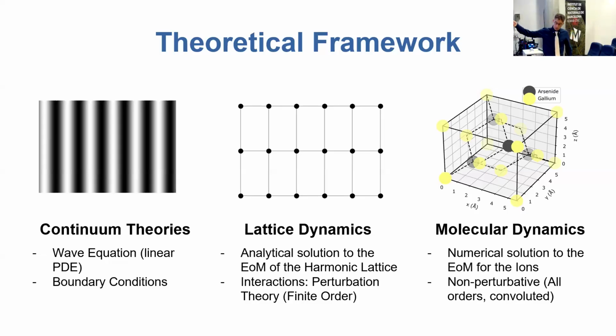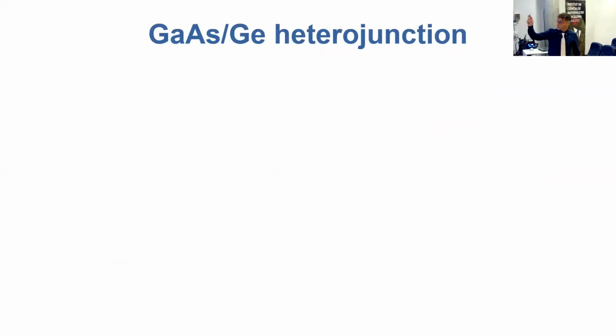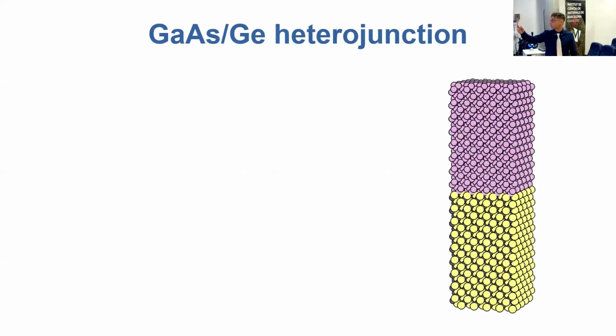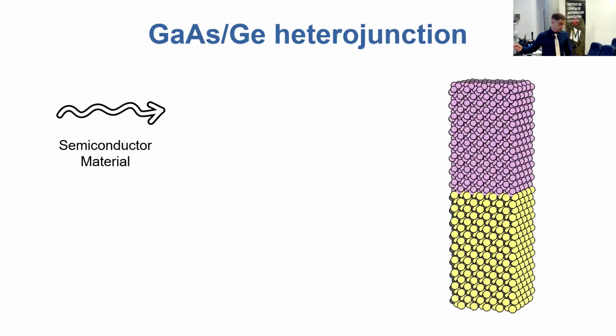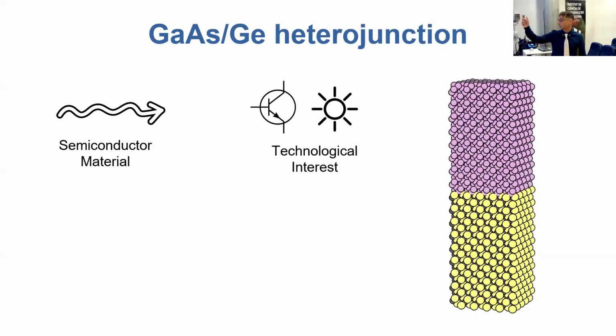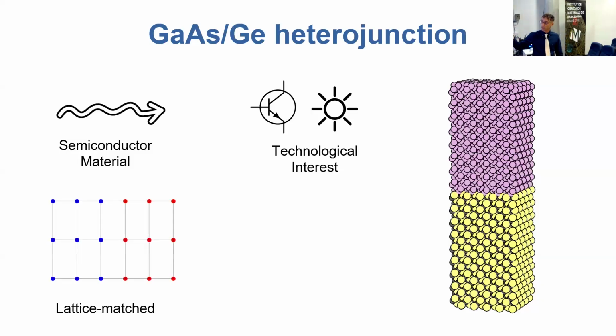And this is the means that we have chosen to carry on our study, thanks to its simplicity and direct comparison with the experiments. The case study is provided by the gallium arsenide germanium heterojunction. Here I give you a snippet of it. Why gallium arsenide germanium? Well, both of them are semiconductor materials, meaning that the phonon is the principal heat carrier inside of them. The second reason is that it has a great technological interest. This junction can be found in high performance and high energy transistors and high efficiency solar cells, and they are lattice matched materials, meaning that this junction can actually exist in nature, let's say at room temperature, without external constraints forcing the junction to exist. This is not a metastable state or something.